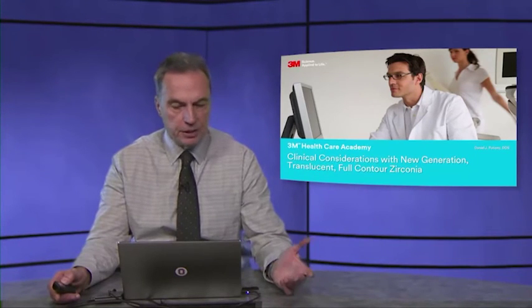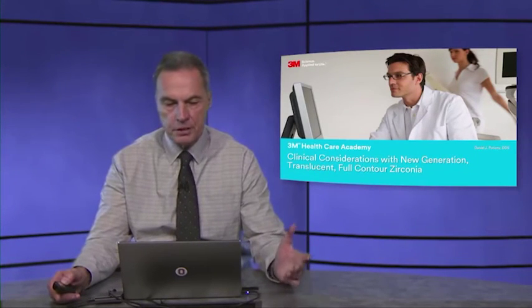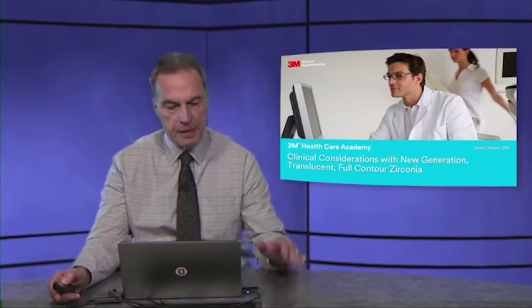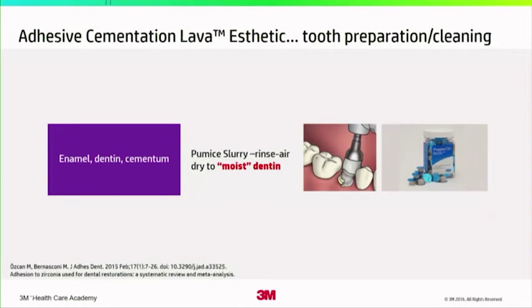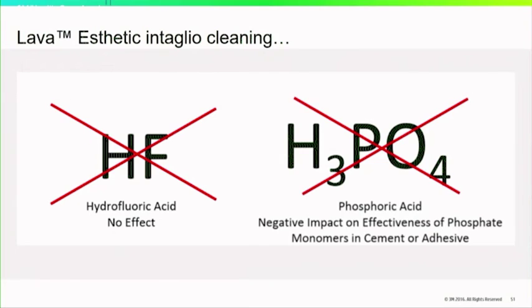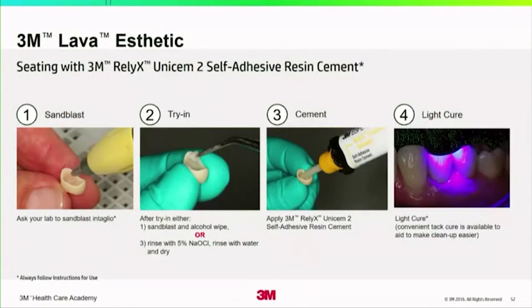Adhesively, when you want to cement a Lava aesthetic, the tooth preparation concept is simply going to come into play. Make sure your dentin is moist. That's a requirement whether you're conventionally cementing or bonding your restoration in. Clean the restoration and the tooth preparation properly. Do not use any type of acid on the intaglio surface of the material, because hydrofluoric acid has absolutely no effect, and orthophosphoric acid, 35%, 38%, has a negative impact because it contaminates the restoration with phosphates that are also present in saliva. It's very simple.